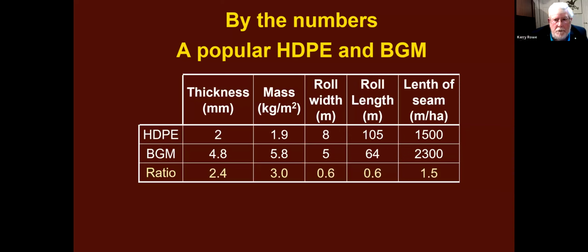We do the same thing for the BGM. Its thickness was 4.8 millimeters, and as you've heard, they are substantially thicker and heavier at 5.8 kilograms per meter squared. The roll was 5 meters wide, 64 meters long, and that gives us 2,300 meters per hectare, or about 50% more welded distance with the BGM that I picked for this particular example and the HDPE I picked for this example.